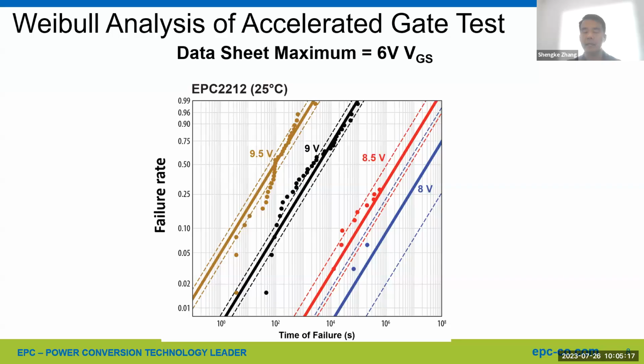We conducted accelerated gate reliability testing, where we took our devices well beyond the datasheet limit and monitored how they fail. Here is the Weibull distribution plot of the test results, where the vertical axis is the failure rate and the horizontal axis shows the time of failure in units of seconds.